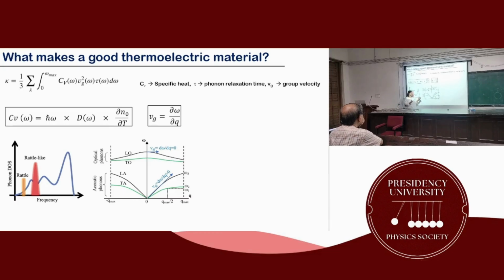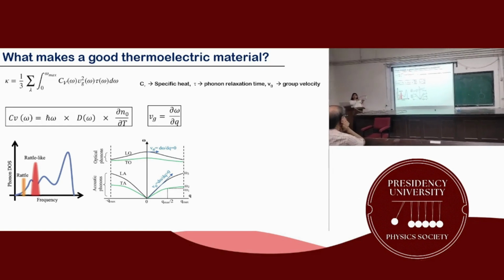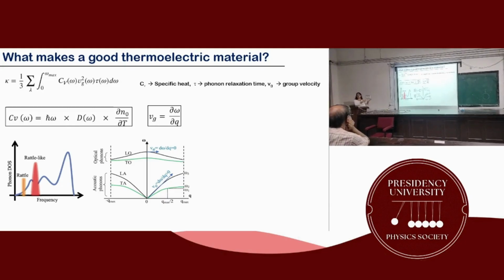But there is a problem: we can never get only flat phonon modes, because we will also have these low frequency phonon modes which can have high vibrational energy in all your reciprocal space, compared to the optical phonon branch. So we will have some kind of mixture of this. But for a material, if I plot the phonon dispersion, I would try to see how flattened my bands are or what type of slope I can get in total, and then I can intuitively understand that maybe this can give me some low thermal conductivity. So let's go with this. So this goes for group velocity.